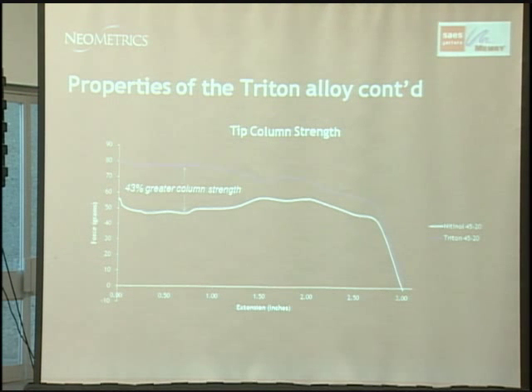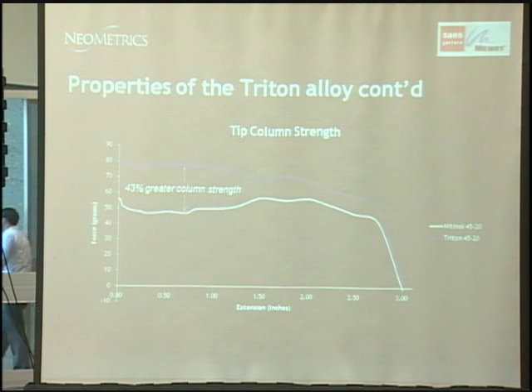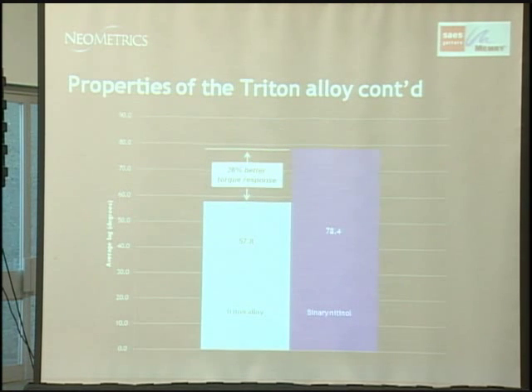In terms of pushability, we've also measured this in our laboratory under various test conditions. We can share our test method with you if you'd like, but we're measuring about a 43% increase in the pushability of the material as well, which is also a function of the material's peak loading forces. In terms of torque response, we've eliminated a significant amount of the torque lag seen with binary nitinol, and in terms of actual torque transmission, we get about a 28% better torque response.